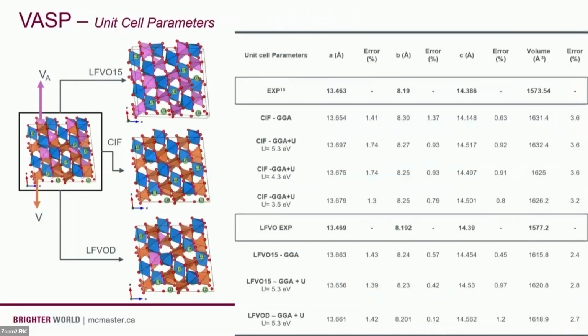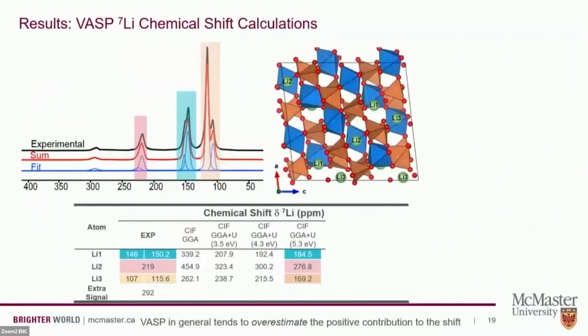So the first thing you do is the geometry optimization. We walked through this. The experimental data for the 2 different structures are shown in the boxes. And the important thing to notice here is no matter which value, either GGA itself or GGA plus U with different values of the U factor, the volume of the unit cell, the overall unit cell structure is not changing significantly. So that's reassuring to us. We can go ahead now and calculate the chemical shifts of each of these structures.